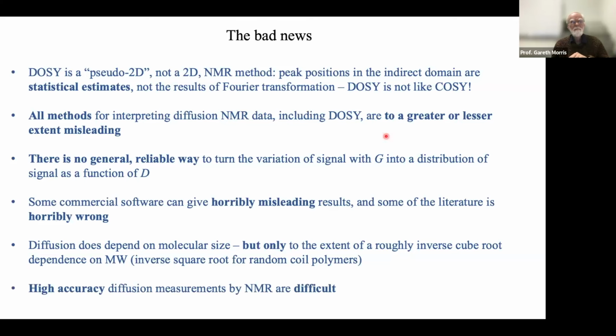And then just a warning that if we want to make really accurate measurements, that's quite challenging. The results of diffusion NMR experiments depend on the quality of our experiments, yes, but also very much on the quality of our equipment. And of course, diffusion is a phenomenon which is very temperature sensitive. So there's not much point in being able to measure D to 1% if you can't measure T to a Kelvin or so.